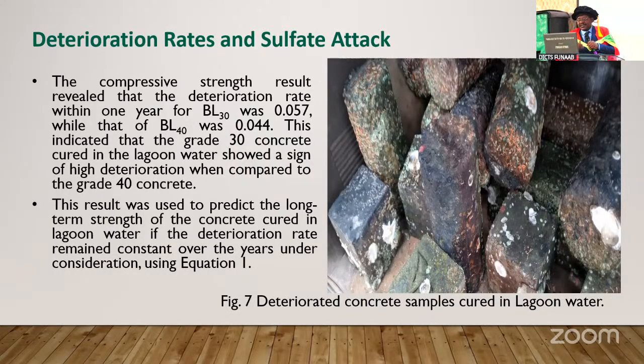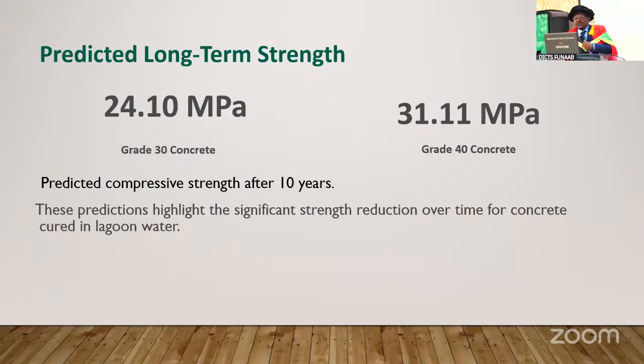We can see some deteriorated samples of the concrete that we cured in the lagoon. You can see how dirty it is, carrying so many organisms on it. Now, using that equation 1, we were able to predict the strength of concrete after 10 years. For the grade 30, the strength reduced to 24.10 MPa, while for the grade 40, it reduced to 31.11 MPa. This prediction highlights the significant strength reduction over time for concrete cured in lagoon water. We are going to see the reason why now.